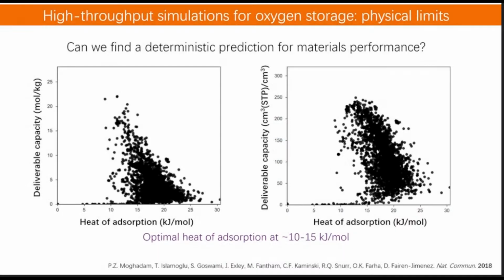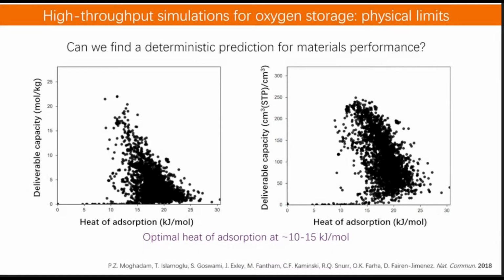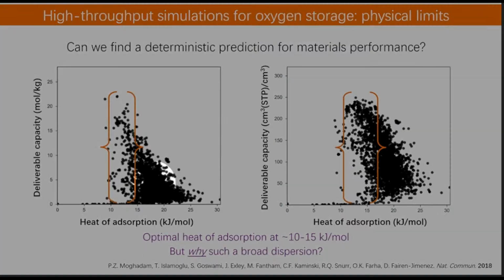This is at high pressure, applying 140 bar. But what we can see is that optimal materials are going to have a specific heat of adsorption, which is basically related to the interaction between the oxygen and the metal organic framework. And this is good, but it's not too good, because if I say an optimal heat of adsorption, an optimal interaction, is these values, we have very good materials, but we also have really bad materials here. So why this big discrepancy? Why this big difference?